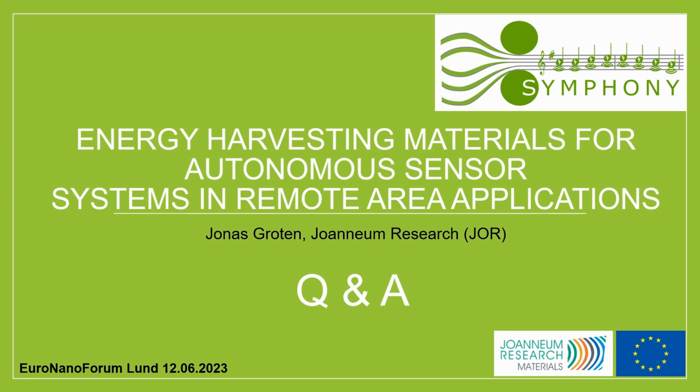Yeah, I mean, in this project we are not looking into putting something inside the body. PVDF is used for medical applications, so it could be possible. We have done pulse sensing with PVDF outside, but not self-powered so far. I think there should be energy available on the body, but for this piezoelectric sensing you need quite some motion. So in the elbow there's maybe enough energy, but inside the body I would rather go for biofuel cells or something like that to take the blood sugar for energy harvesting.